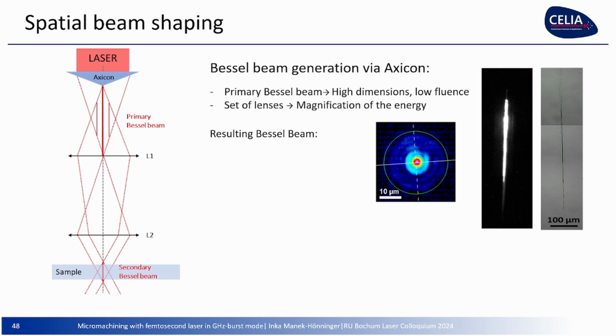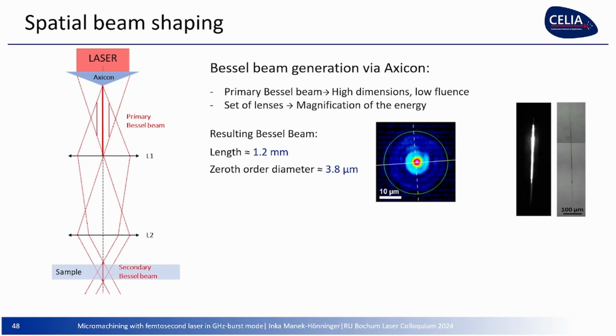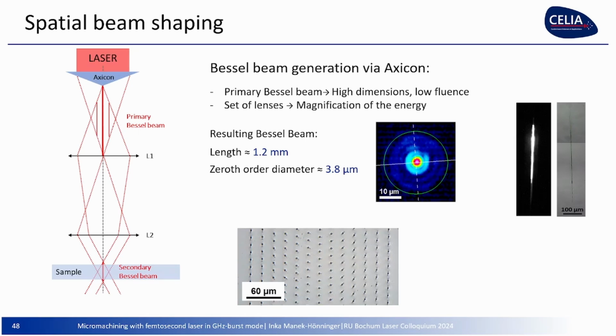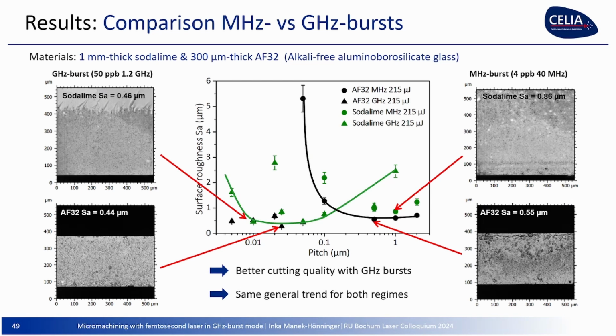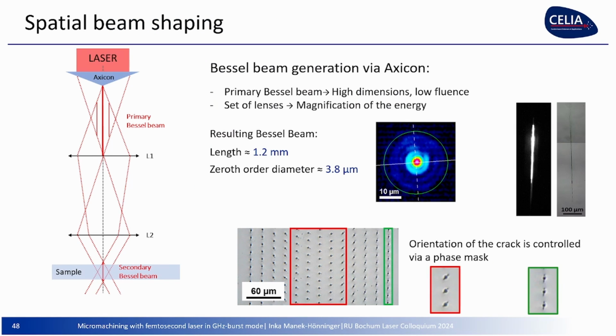The measured beam, you can measure also the length of the Bessel beam by fluorescence or post-mortem, once again in soda lime, as it costs nothing. You can have a look at the length of the modified material. And what we got is 1.2 millimeters length and almost 3 microns in diameter. And what happens when you look from above on your soda lime sample? So what you can see is you have holes, but there's something around, some crack around, and you have to orientate these cracks. If the translation movement of the sample is like this, you have to align the cracks in the same direction as you're moving the sample in order to cut. In this way, it will not really work. And we can do it by turning a phase mask.